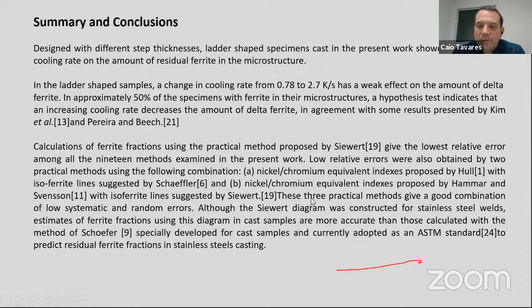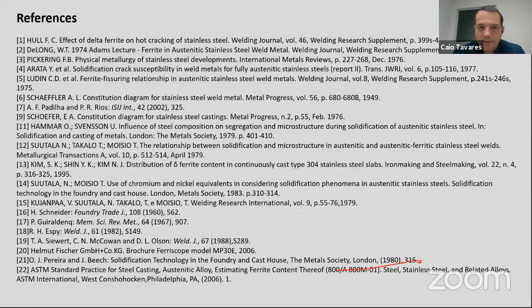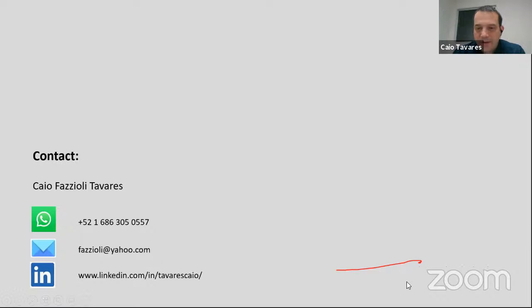So those three practical methods give us a good combination of low systematic and random errors. Siewert was constructed for stainless steel welds, but even though this diagram was constructed for welds, it worked well with the castings. So it was very good to predict the ferrite in castings, and more accurate than the calculators by Schoefer that were specially developed for castings. And that is current in this ASTM standard to predict the ferrite fractions of the stainless steel. Here are the references. I think I made it quicker than planned.